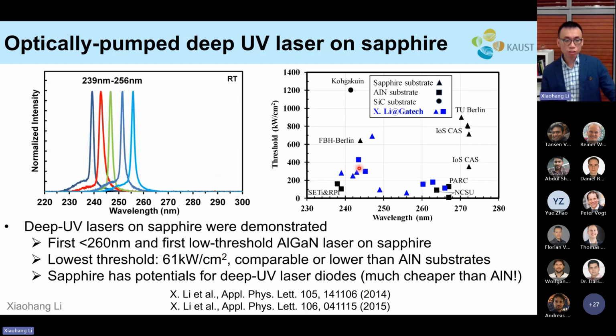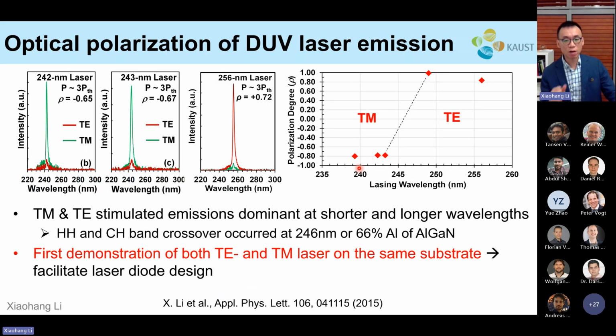So in addition to demonstrating the lasers and looking at the threshold, another important property of the AlGaN-based system is the optical polarization, because depending on the relative position of the split off hole band and also the heavy hole valence band, you can have either the transverse electric or the transverse magnetic emission. Right, so when you have the recombination between conduction band and then the heavy hole valence band, you have the TE polarization. And when you have the recombination between the conduction band minimum and then the split off band, you will end up with a transverse magnetic emission, right?